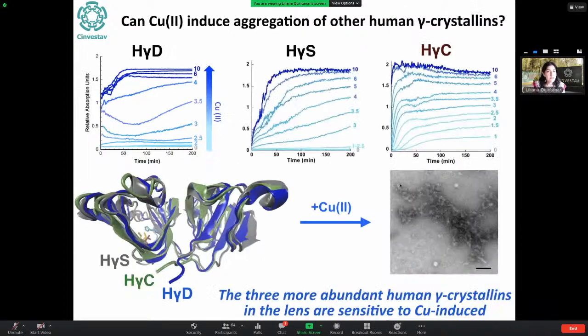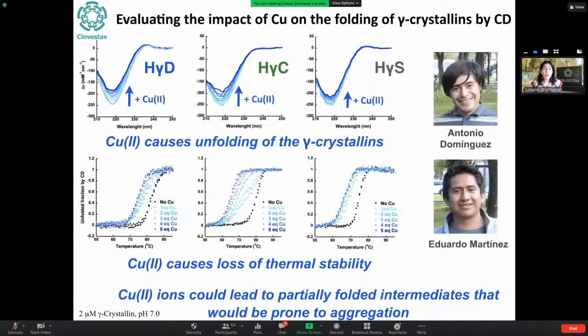We later found that all three gamma crystallins, gamma D, gamma S, and gamma C, have a very similar fold. They are rich in beta sheet structure. All three are susceptible to copper-induced non-amyloid aggregation. So we asked about the mechanism, and this is the early work done by circular dichroism by Antonio Dominguez, a former student in my group, and an undergrad, Eduardo Martinez. They did titrations of these proteins by circular dichroism and added the metal ion. These proteins are rich in beta sheet folding, so they have this negative signal here at 218 nanometers. And as we titrate the metal ion, we can see a decrease in the signal, suggesting that the beta sheet fold